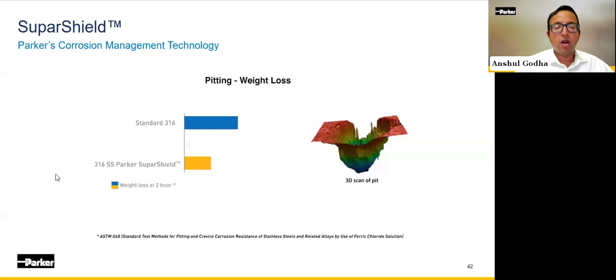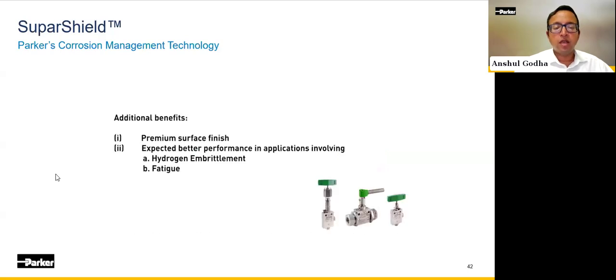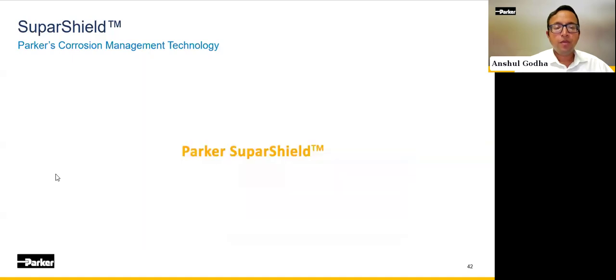But the benefits are not just limited to stress cracking. We see improvement in other forms of corrosion as well. For example, with pitting, we see up to 50% reduced weight loss. Moreover, on top of it, we also see a better surface finish with this product, as well as significant improvements in hydrogen embrittlement, as well as fatigue. We will be sharing more about that in the future.